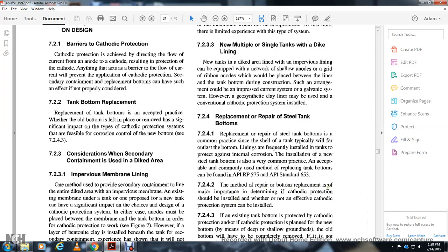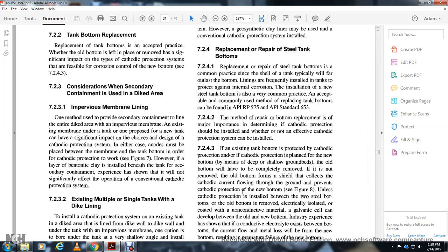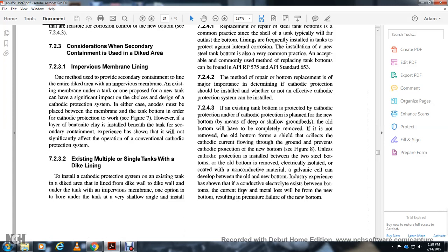The method of repairing the bottom is of major importance in determining whether or not an effective cathodic protection system can be installed. If the existing tank bottom is protected with cathodic protection and is replaced with a new bottom, meaning the old bottom will not be completely removed, the old bottom forms a shield that collects the cathodic current through the ground and prevents the cathodic protection of the new bottom. The cathodic protection is installed between the two steel bottoms.